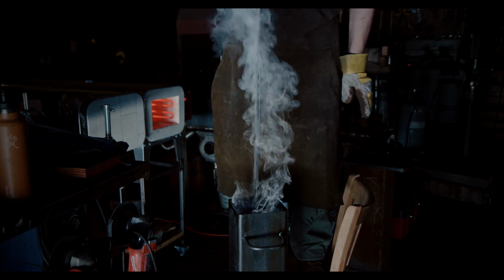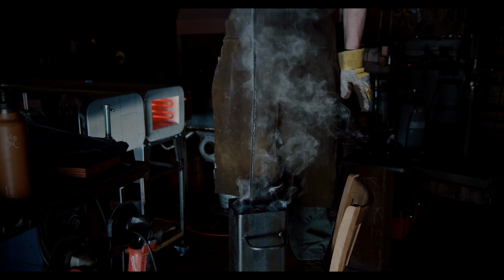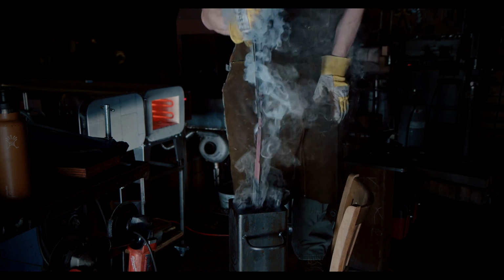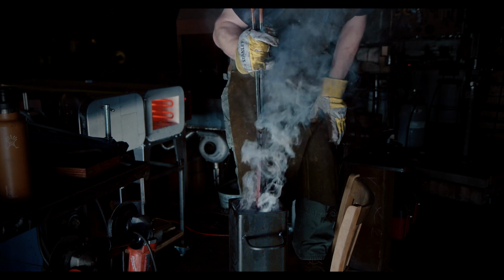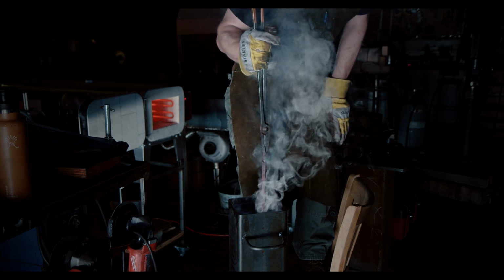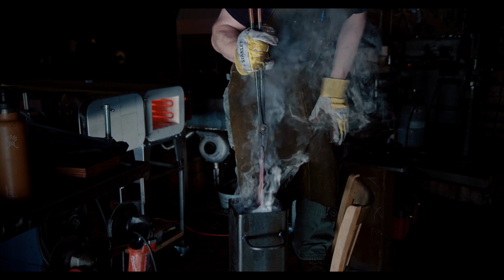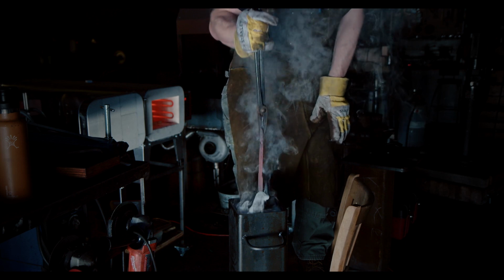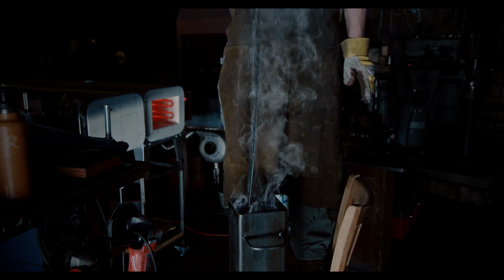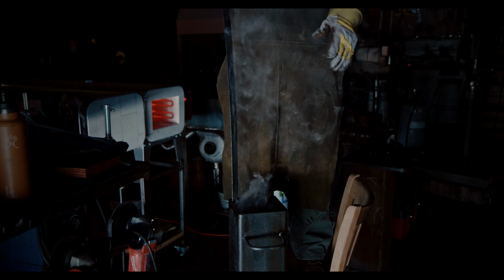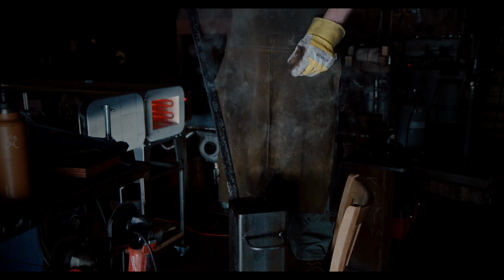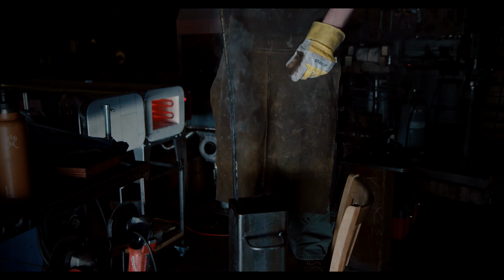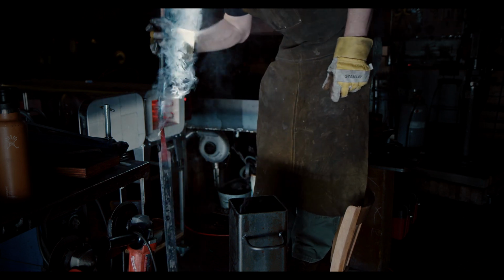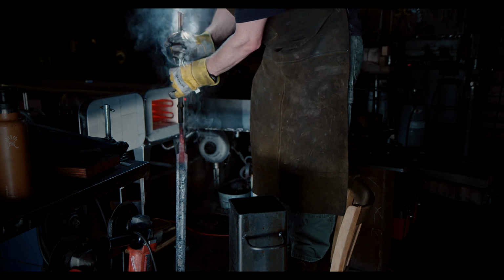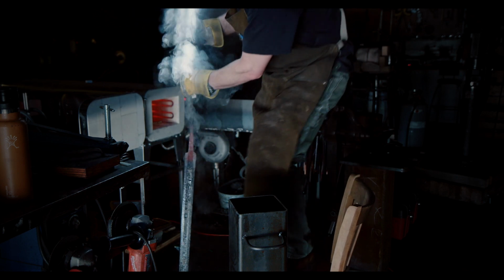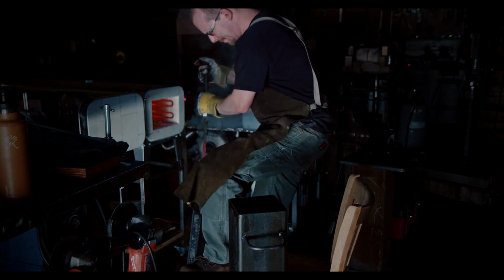As I pull the sword out of the quenching oil, a bend is clearly visible. Unfortunately, in the low light, I have not quite noticed it yet. Another surprise, also clearly predictable, is that the sword is too long for my quench tank. In practice, this does not really matter, since the cutting edge close to the hilt will not see any action. In the heat of the moment, a little correction may help, but I will address the bend more systematically during tempering.